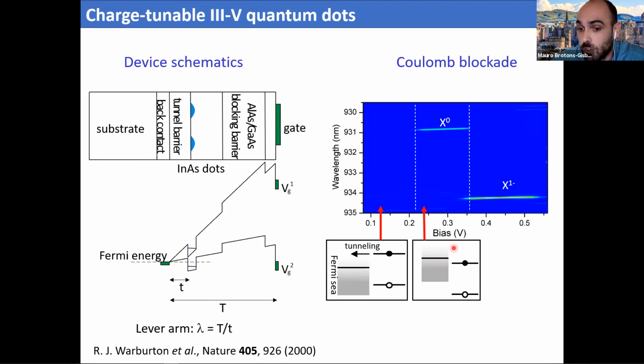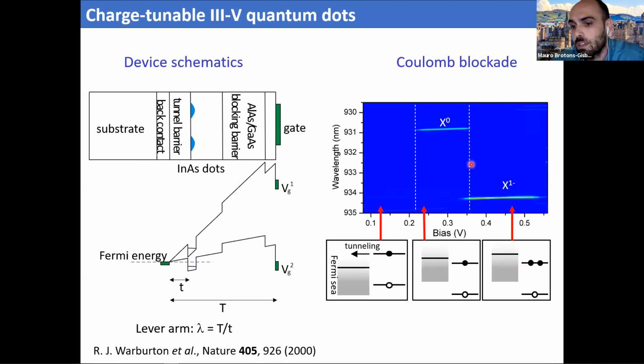But now one could think that a second electron could also be loaded in the quantum dot. But the point here is that due to the presence of the first electron, in order for a second electron to tunnel inside the quantum dot, this second electron has to overcome the Coulomb repulsion with the first electron, right? And this is why this is known as Coulomb blockade, because this first electron is preventing the tunneling of a second electron. But now we can keep increasing the gate voltage and increase this energy difference, and this way overcome the Coulomb repulsion and load a second electron. And this can keep going on, so you can keep increasing the voltage and start loading electrons one by one in the dot.